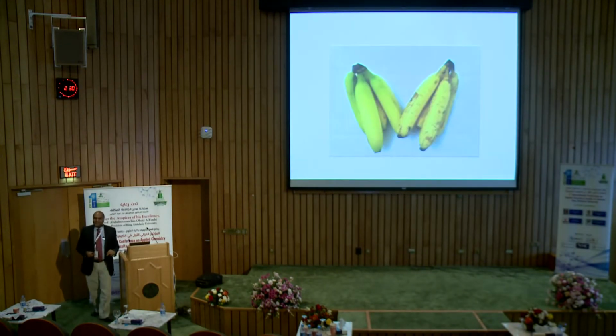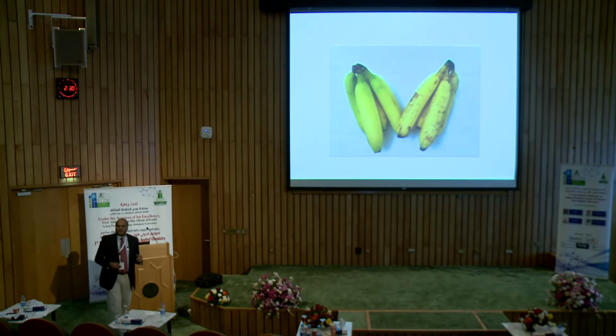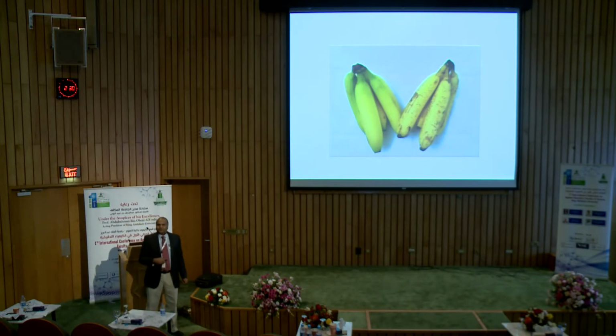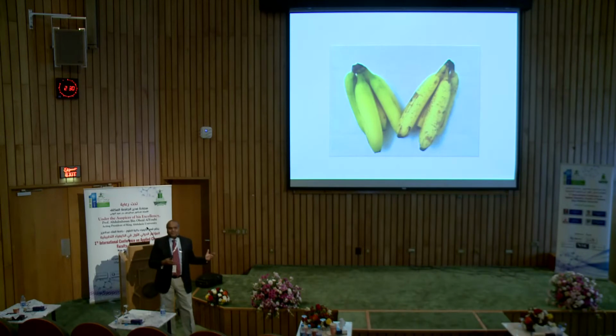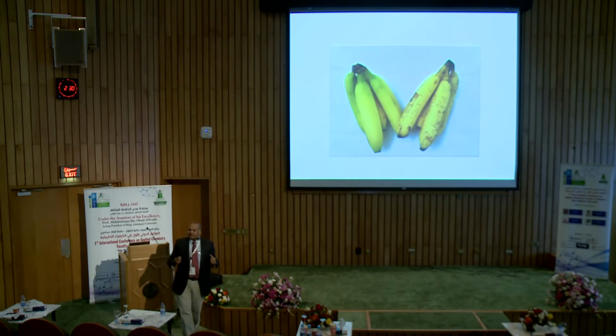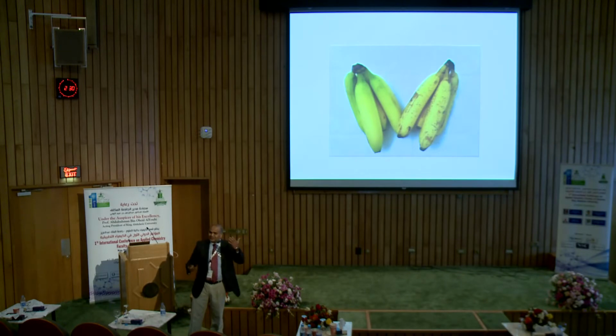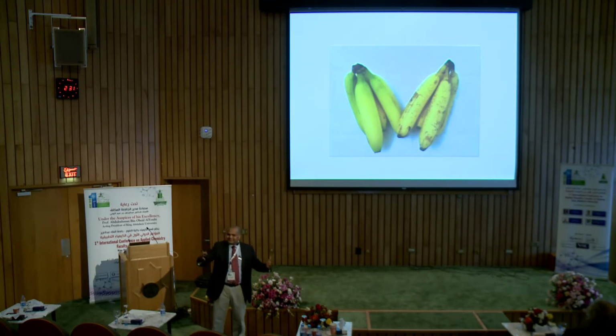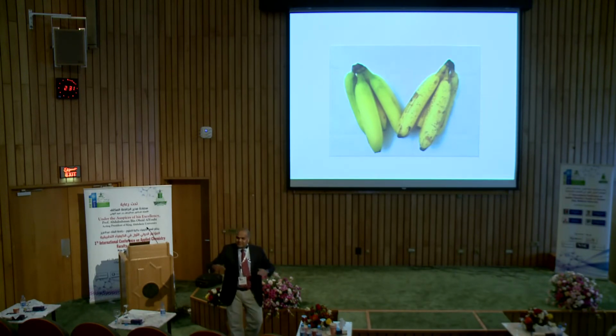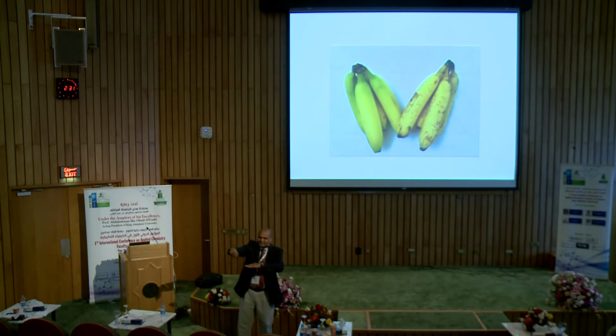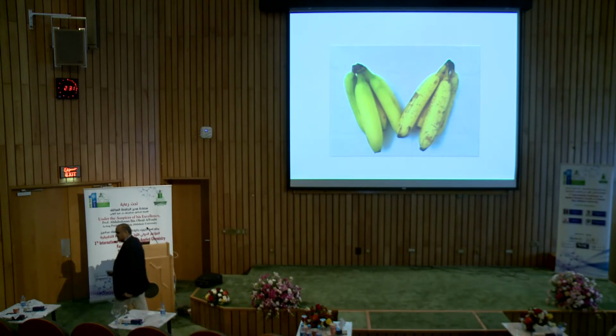Now, this is where, again, I bring the bananas. Some of you have missed this earlier. What I'm trying to say is, if you can look at it, like the microstructures of metals I showed you, you can tell there is a microstructure. But if you can't look at it, suppose your eyes are closed, you can figure it out by pressing it. Which one is that? So if I have a microstructure in organic crystals, I can't see it, right? I can't put it under a microscope and get the domains. But I can poke it and say, here it's soft, here it's hard. There is a distinct difference. Okay, so what did we do?